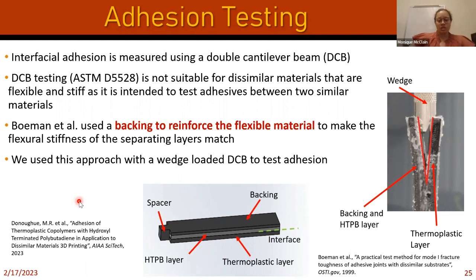The approach we decided to use was essentially a modified double cantilever beam test. A double cantilever beam test is when you have two things together and you're peeling them apart, and they have relatively closely matching bending stiffness. However, the classic version wasn't necessarily the best approach for what we're trying to do, because we have a rubbery material and a rigid material. But we did find someone who modified that. Essentially, to make these two parts bend more equally, you can reinforce the weaker part with some stiff backing. So we did some calculations.